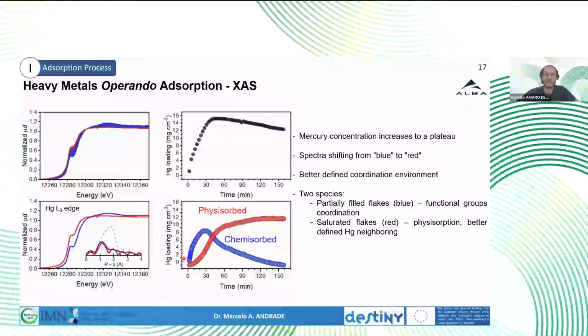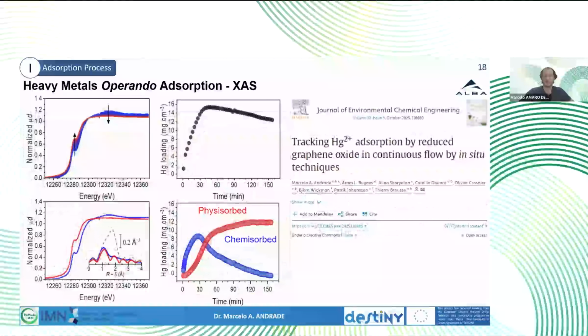the beginning, since we can see it is competitively decreasing with time. So we start really quickly with a chemisorption of mercury, and then the amount of chemisorbed mercury decreases relative to what would be the physisorbed one. And that was intriguing, since physisorption requires a lower activation energy to happen. But that was what we found on XAS, that mercury was first coordinating with oxygenated groups on the surface of RGO, and later it was mainly physisorbed or weakly attached to the foam.